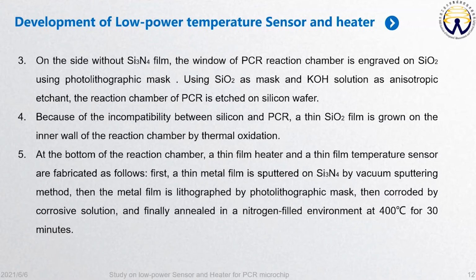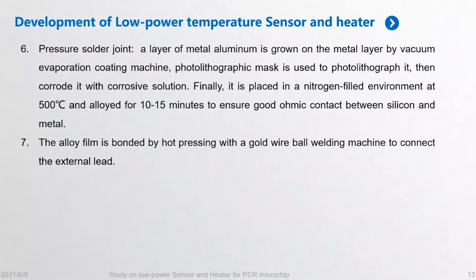And the fourth step is, because of the incompatibility between silicon and PCR, a thin silicon dioxide film is grown on the inner wall of the reaction chamber by thermal oxidation. And the fifth step is, at the bottom of the reaction chamber, a thin film heater and a thin film temperature sensor are fabricated. The sixth step is pressure solder joint, and the seventh step is the alloy film is bonded by hot pressing with the gold wire ball welding machine to connect the external lead.